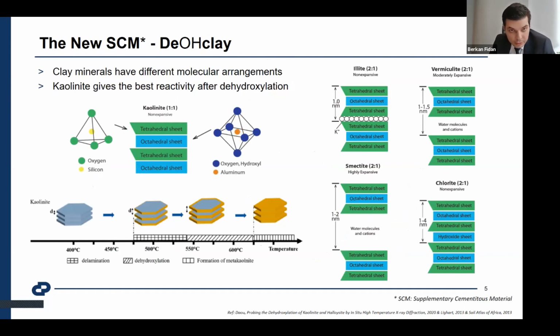The new supplementary cementitious material is dehydroxylated clay, based on a thermal process with known clay minerals. The well-known clay minerals, which are highly available all over the world, are kaolinite, illite, vermiculite, smectite, and chlorite. The crystalline structure is critical here, due to the one-to-one structure of kaolinite, with one tetrahedral sheet and one octahedral sheet. After thermal treatment and dehydroxylation, it turns into metakaolin. Metakaolin is a known product.